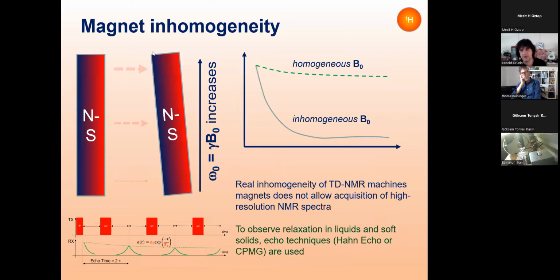Another problem of time domain NMR machines is the inexact homogeneity of the main magnet. Here I just show a typical situation. Magnets are not parallel, and where they are closer to each other, the magnetic field is stronger. Where they are farther from each other, the magnetic field is weaker. And imagine that the sample is located in all these areas, all these regions. So here in the upper part, the frequency, which is proportional to the magnetic field, is higher, and here it is lower. And then instead of the long magnetization decay, you will observe a fast magnetization decay, which is characterized by the so-called T2 star.